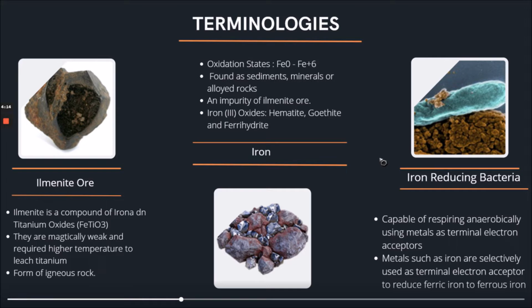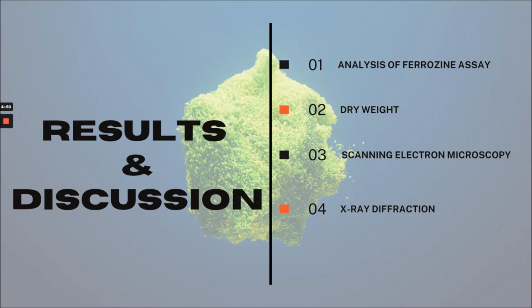In ilmenite, particularly, iron takes the form of iron 3, the ferric iron. They are insoluble in nature and brown in color. This insoluble iron serves as an impurity to the ilmenite ore. Iron reducing bacteria, on the other hand, are unique bacteria with the capability of reducing iron under anaerobic conditions. Under anoxic situations, iron reducing bacteria such as Shewanella oneidensis MR1 are best known to reduce iron and manganese through electron transfer. This is helpful to our project because reducing the iron 3 to the iron 2 form will automatically convert their solubility.